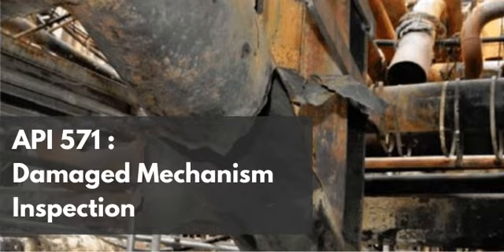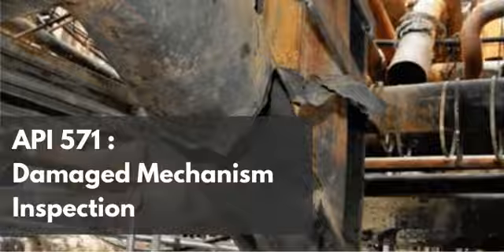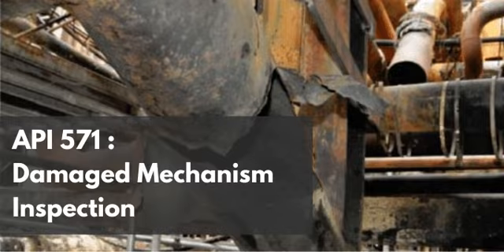Let's start with WFMT. This relies heavily on the physical properties of carbon steel, doesn't it? It does. Carbon steel is highly ferromagnetic. The inspector uses an electromagnetic yoke to induce a magnetic field into the component. So the yoke introduces magnetic flux lines that travel smoothly through the continuous atomic lattice of sound carbon steel. Yes. The inspector then applies a liquid suspension containing extremely fine iron particles that have been coated with a fluorescent dye. But when those flux lines encounter a crack, the physics change. Drastically. The crack itself, even though it's filled with iron oxide, has a significantly different magnetic permeability than the base solid steel. It acts as a region of high magnetic reluctance.